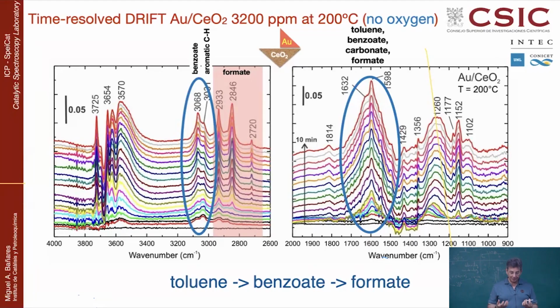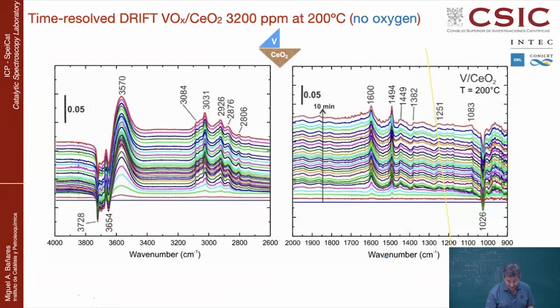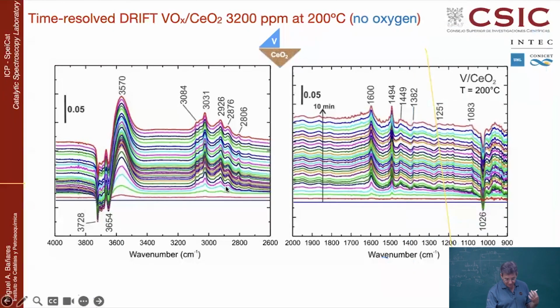Now, in the case of Raman, the infrared, we already made a more detailed study, and then we were comparing the same thing. What happens if I feed toluene to the Vanadia Ceria, which is the less reactive one? Well, in this case, when you adsorb toluene, basically you observe that this region here of the CH, of the adsorbed hydrocarbon, remains like that, and you hardly get any oxidation to the benzoate.